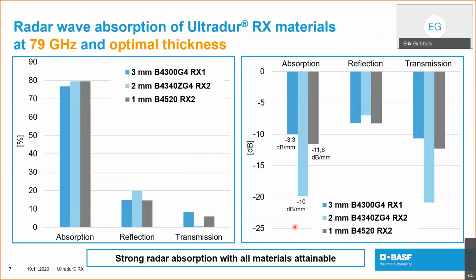Now let's move on to the Ultradur RX materials and their performance. Here you can see the 3 materials I've just introduced to you at their optimal thickness measured at 79 gigahertz. So 3 millimeters B4300G4 RX1, 2 millimeters B4340Z G4RX2 and the unreinforced B4520RX2. The first noticeable result is that all materials at their optimal thickness are strong absorbers, absorbing almost 80% of the incoming power. Reflection was found to be between 15 and 20%, depending on the material, and the transmission generally below 10%, for some materials even below 5%, showing materials can absorb a large amount of the incoming radiation.